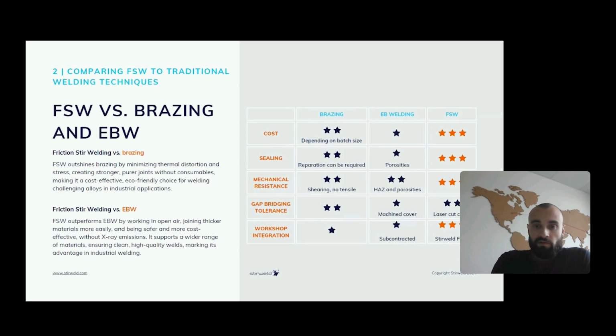So brazing consists in a filler material which will melt, but without melting the edges of the parts to be brazed. It is usually performed in a furnace under inert atmosphere or under vacuum. So from a cost point of view, brazing can sometimes match the cost efficiency of friction stir welding if we are looking at large batches, but this is only if we look at the direct cost of the brazing process, that is the energy consumption, the consumable, and the time to be spent in the furnace.